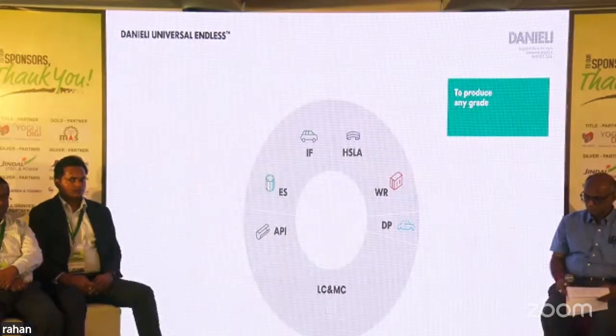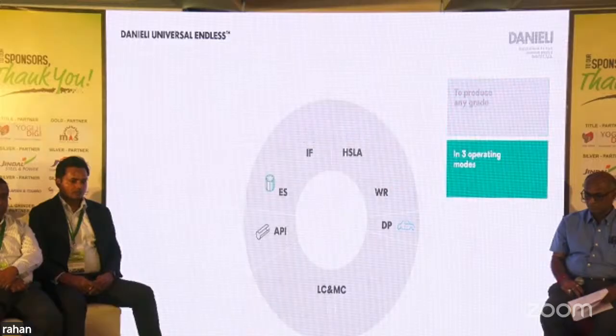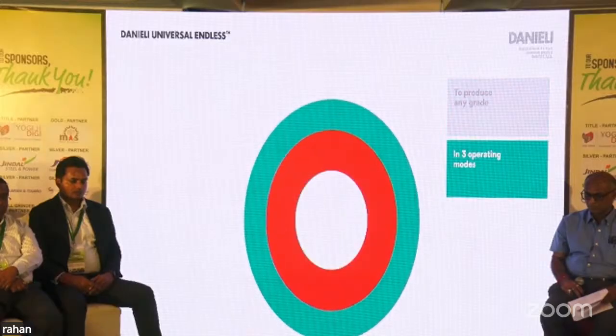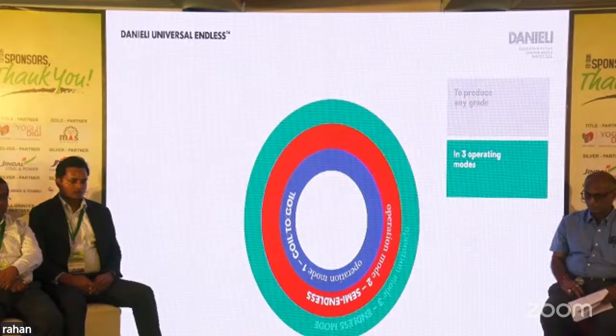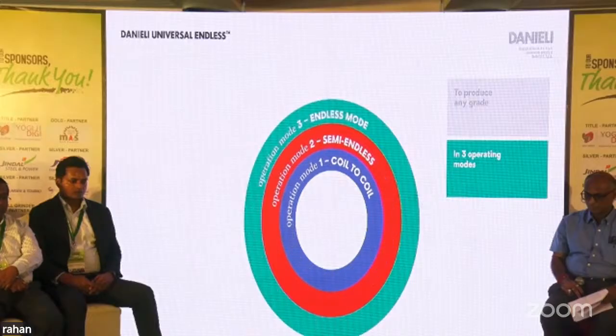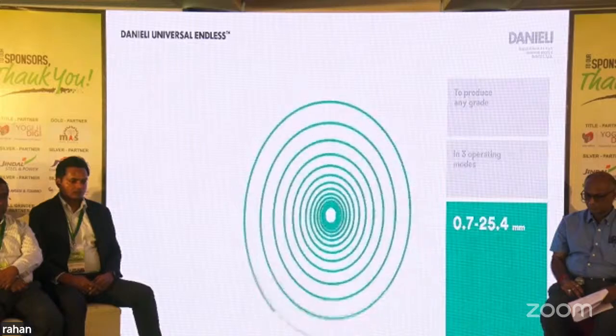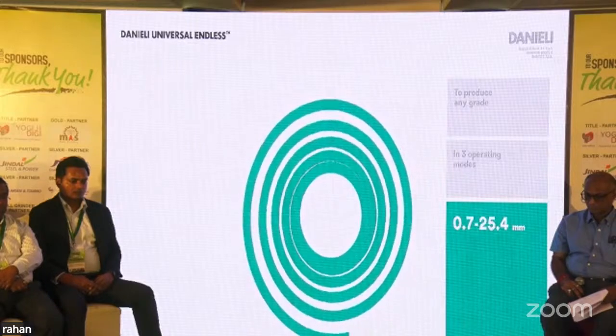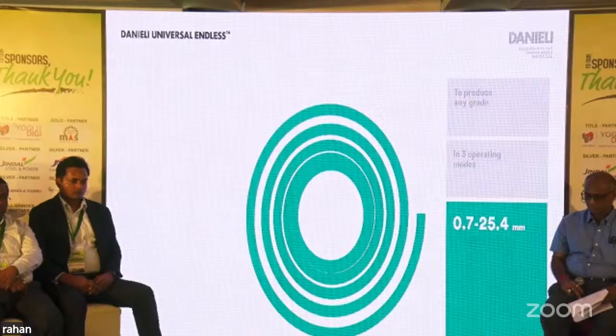Until now, the policy was that if you would like to have low carbon steel, then let's put up a TSCR. If you would like to have conventional grades like API, put up a hot strip mill. So you are putting up two rolling mills for different uses, and that is where it can be combined. This is about the 3 operating modes that I mentioned, and I also briefed about the advantages each mode has. Then the thickness range is 0.7 to 25.4 mm, thinner to the max.